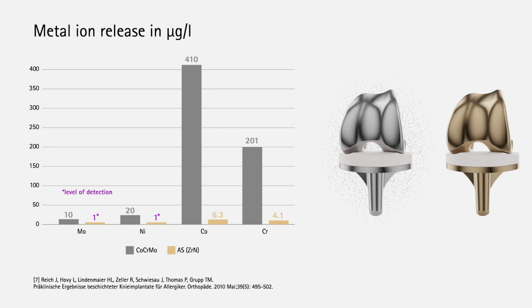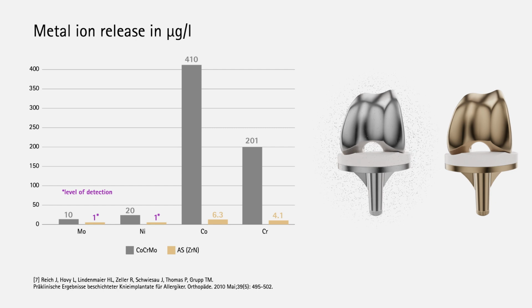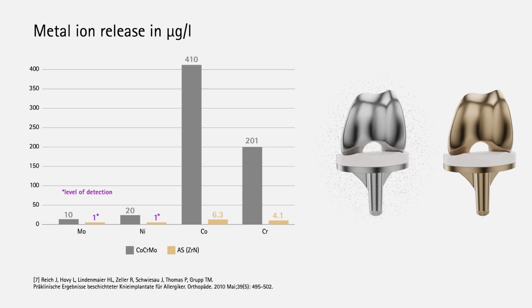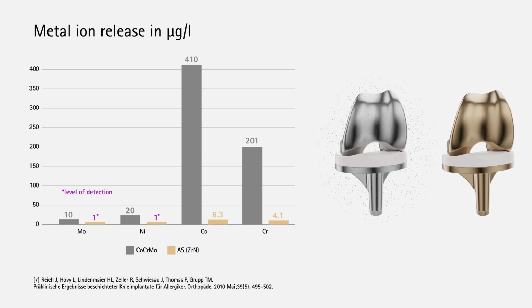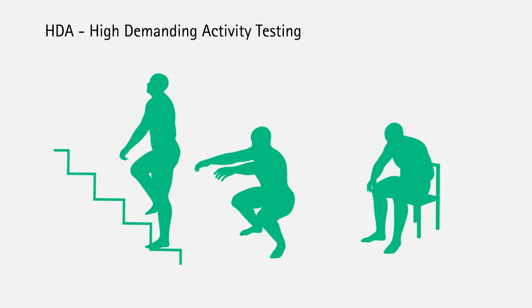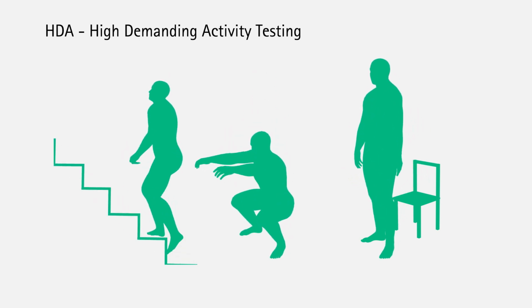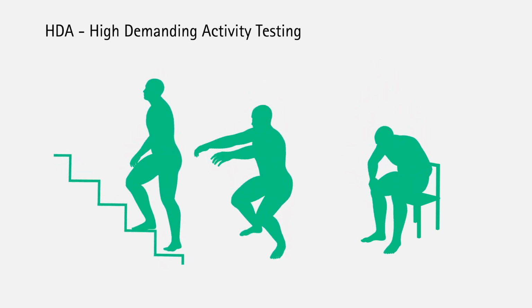The release of cobalt and chromium is quite high compared to the release of the metals from an implant with advanced surface coating. With the AS multilayer coating, metal ion concentration is near the level of detection and below biological threshold. This means that the higher risk of a hypersensitive reaction could be reduced by using a multilayer advanced surface coating. We developed additional test methods that exceed the common ISO test procedure.